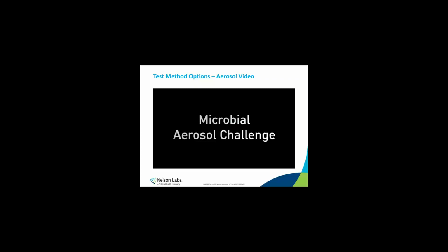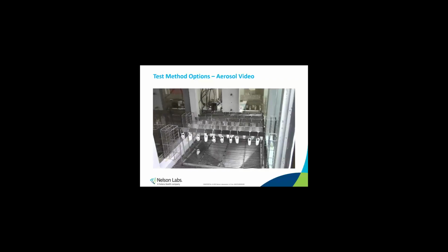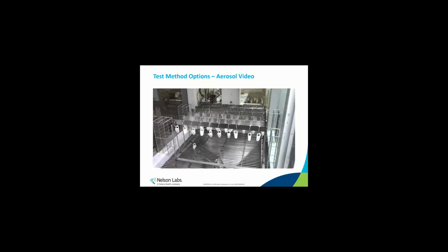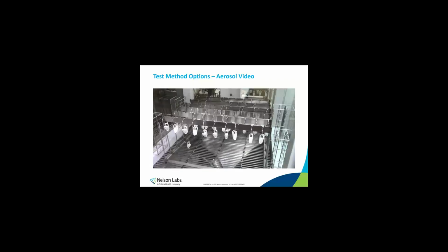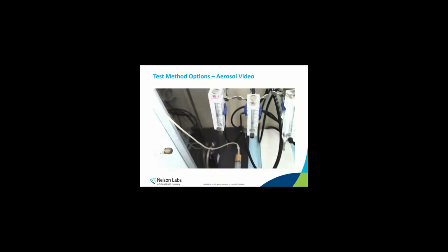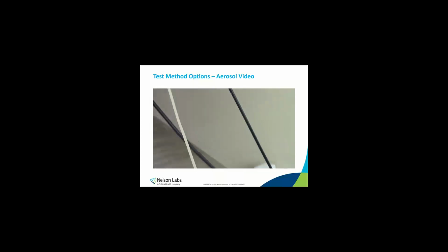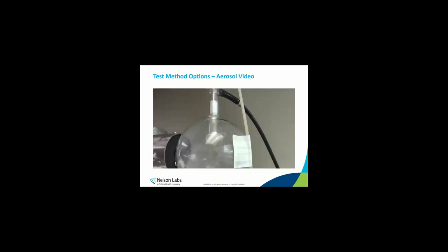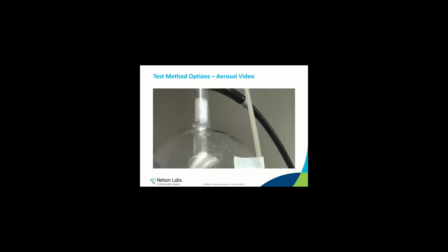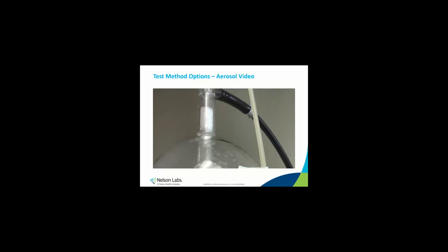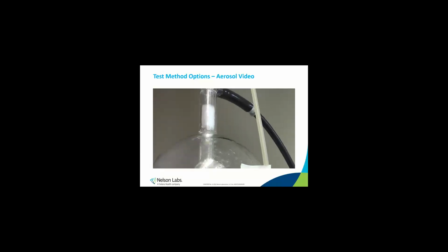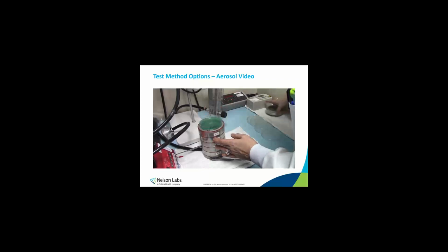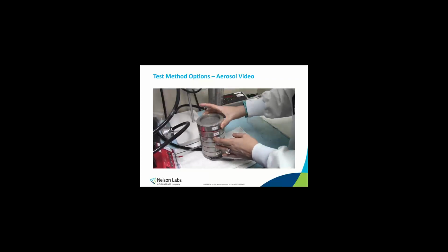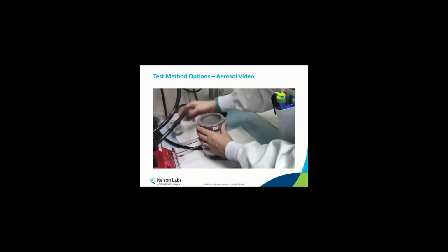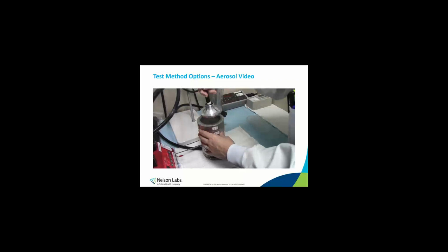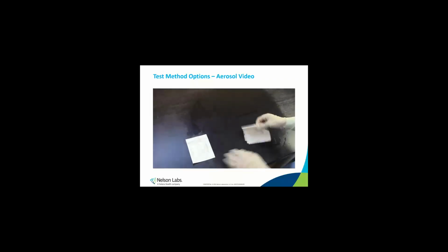This is going to test the whole package, not just the material. We have a customized chamber. We're going to put them in the chamber and space them out to expose as much surface area as possible. And then we're going to use another nebulizer to aerosolize the Bacillus atrophaeus so that it can distribute throughout the chamber. We're going to monitor our chamber using Andersen samplers to get a mean particle size.